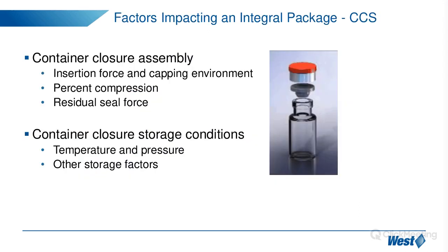Not just cold storage — for a syringe or cartridge system, pressure and temperature conditions are also critical. For example, a change in pressure could cause movement of the plunger through the barrel. The differential in pressure could cause the plunger to move, which itself could cause a CCI breach. This illustrates why for different drug products we need to consider how the package behaves at its different lifecycle stages and where the failure modes are.